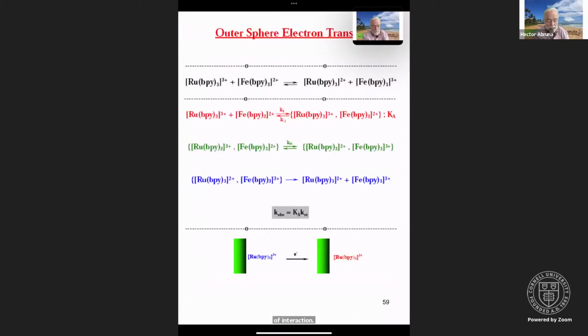So if we look at outer sphere electron transfer, here we're looking at the reaction of tris(bipyridyl)ruthenium-3 and tris(bipyridyl)iron-2. This species is more than capable of oxidizing the iron-2. So this would be in equilibrium with ruthenium-2, which is the reduced form, and iron-3, which is the oxidized form. So how do we imagine this taking place? You have the two reactant partners, the ruthenium-3 and the iron-2. They form an association complex, and there's an equilibrium constant associated with this, and that's why we put the little brackets here to reflect that this is an entity usually separated by some solvent sphere.